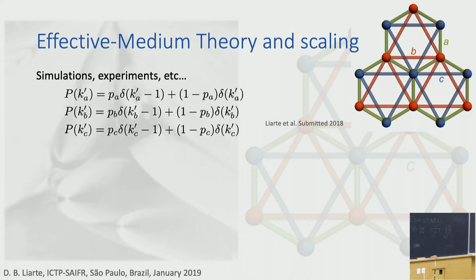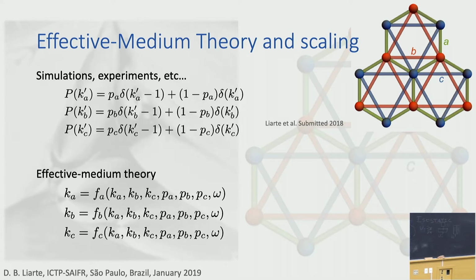You can do experiments. You can 3D print each of these lattices, for instance. But the nice thing about these random elastic networks is that you can actually use effective medium theory and solve for the properties of these lattices. And I'm going to skip the details again. In the effective medium theory, you have a set of effective spring constants, Ka, Kb, and Kc, and they satisfy a set of self-consistent equations that will depend also on the 3 probabilities and on frequency as well. So you have a pretty robust description of the whole jamming transition, including dynamical behavior.